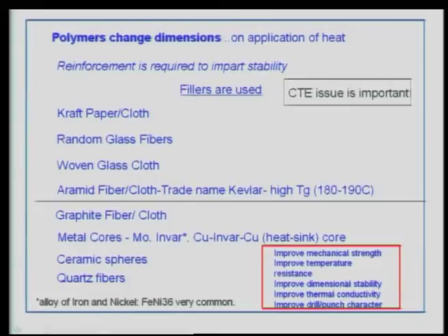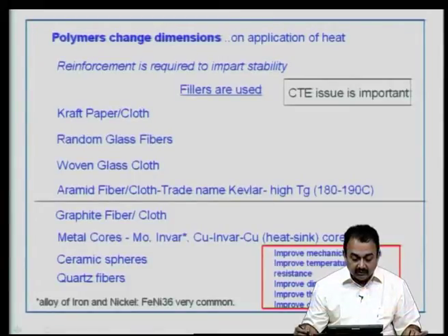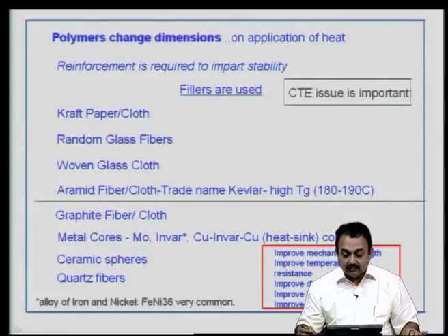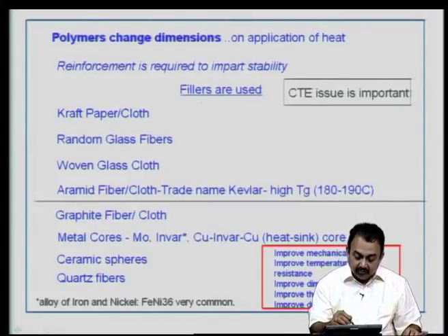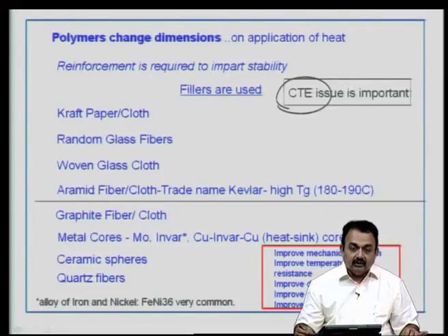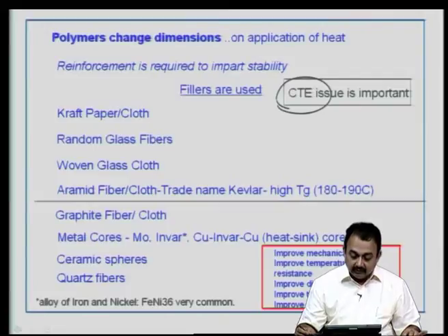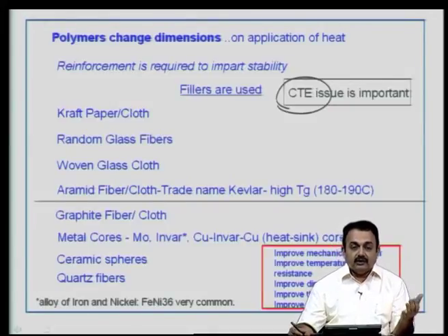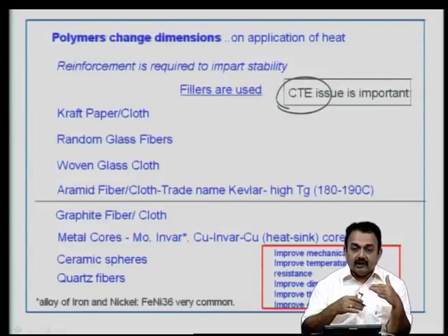Now, polymers change dimensions on application of heat. Reinforcement is required to impart stability to the system. That is the reason why we use fillers. So, when we modify the material with fillers, you are modifying the CTE, coefficient of thermal expansion, which we have seen when we discussed the packages, how the CTE of a silicon die and the CTE of an organic substrate have a huge mismatch, and we try to